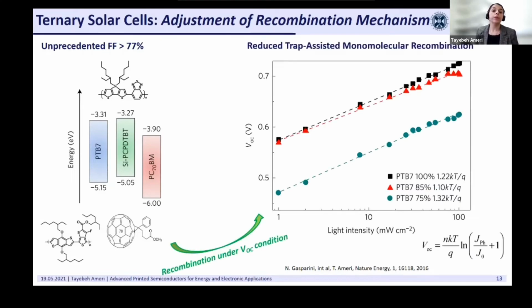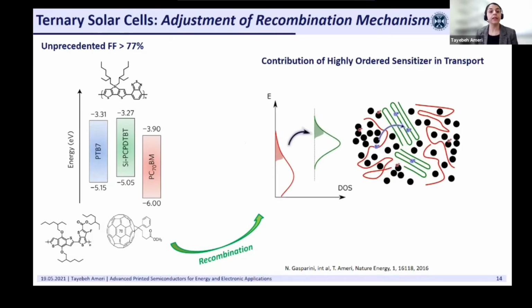And our recombination study under the open circuit voltage condition showed that indeed, by introducing the sensitizer, we are reducing the trap-assisted monomolecular recombination in the system, which relies on the fact that by a smart design of the ternary system, we let our charge carriers be transferred from an amorphous, trap-dominant host system like PTB7 to a higher order sensitizer with a narrower density of states like silicon PCPD-TBT. And then when this highly ordered sensitizer starts to contribute in the transport, it can adjust the recombination mechanism and improve the fill factor significantly.